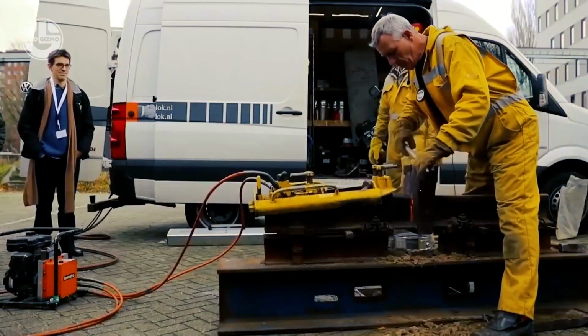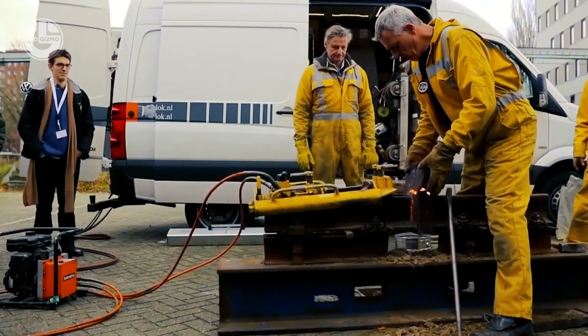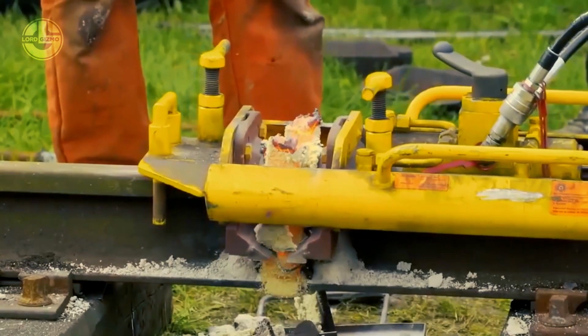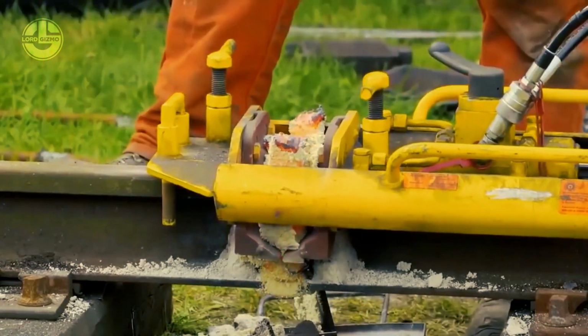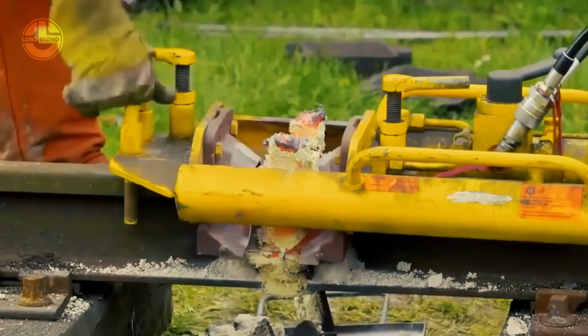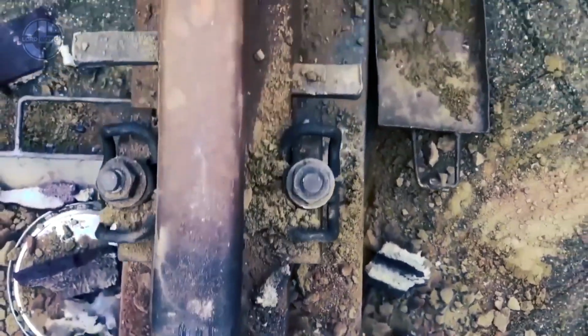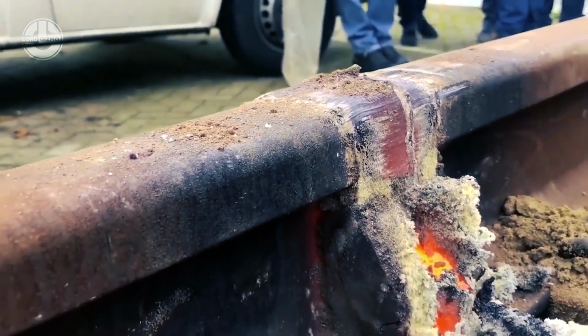Number 7. Post-weld inspection and cleaning. If it's done and cooled, they'll start taking the mold off the metal and check the weld junction for quality. They also use grinding or other cleaning techniques to remove any extra material or slag produced during the welding process.